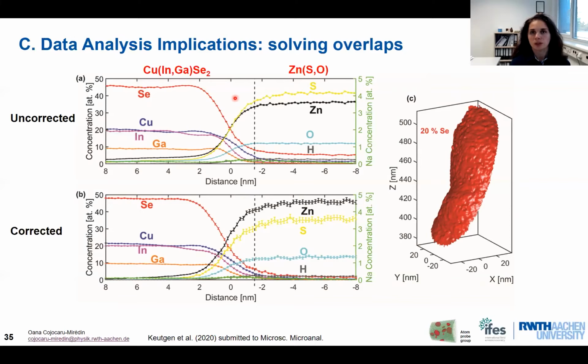It had been long stipulated by the solar cell community that at the CIGS surface, we have a copper depletion region. And this copper depletion region would mean that we have a preferential segregation of copper vacancies on the CIGS surface. But then the question was, what happens when a buffer is deposited on this absorber surface?